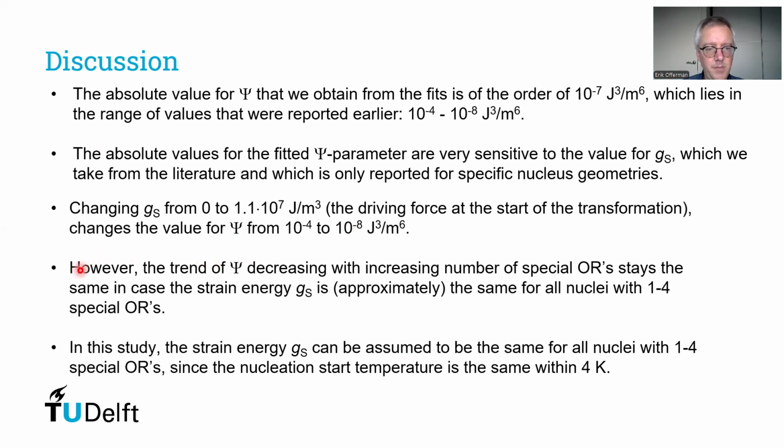So the trend of decreasing psi value with increasing number of special crystallographic orientation relations stays the same in case the strain energy is approximately the same for all the nuclei with the 1 to 4 special orientation relations.